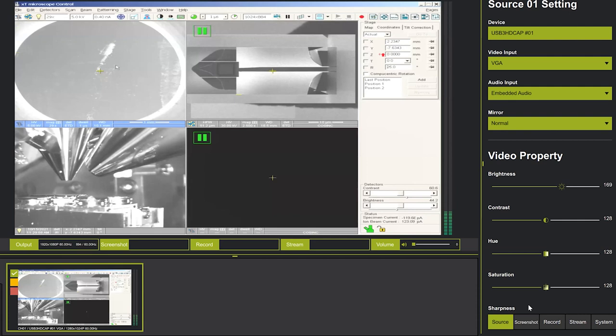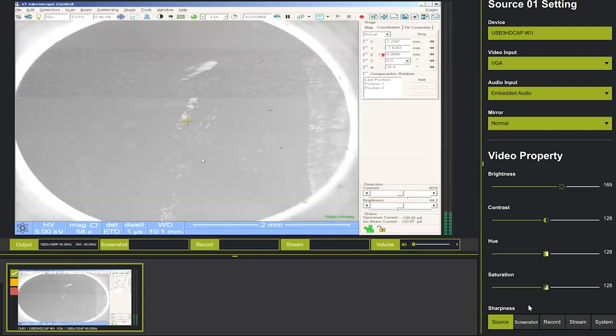So this top left window is electron beam in, secondary electron detection. So this is the typical SEM image. Top left is the SEM image. Top right would be the ion beam image. So that means ion beam in, secondary electron out. I don't have any detector to detect secondary ions. So what I'm detecting is secondary electrons using the same detector for both top two. It's always the same. I have to find the sample.